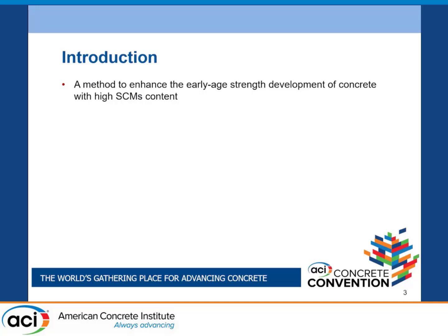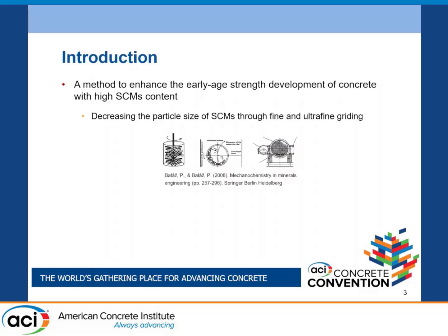A method to enhance the early age strength development of concrete with high SCM content is to decrease the particle size of SCMs through fine or ultra-fine grinding. Nowadays there are different types of mills that can reduce the particle size of any material. In the literature we can see some examples of ultra-fine grinding applications for conventional SCMs such as fly ash and slag. If we reduce their particle size, we increase their reactivity, and they can contribute more effectively to the strength development